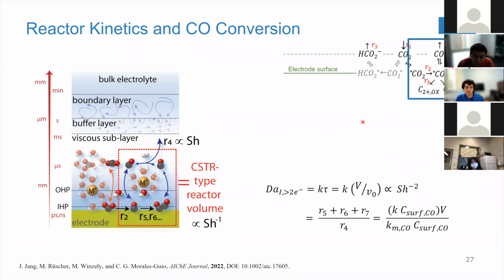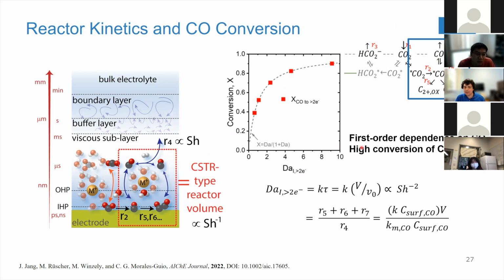Let me just jump to the results. What we say is simply that this is really a first order process on the concentration of CO, but the products that you see are a combination of that first order reaction rate, multiplied by tau, the residence time, as shown here. So we can separate intrinsic kinetics from mass transport properties, things that you can change with the hydrodynamics. This Damköhler number, effectively K, is intrinsic kinetics, and tau is just a function of mass transport.